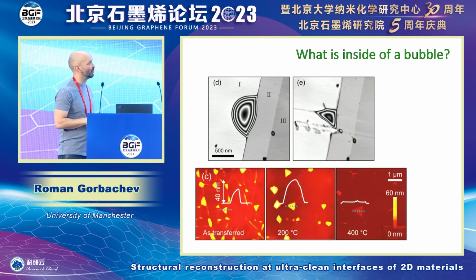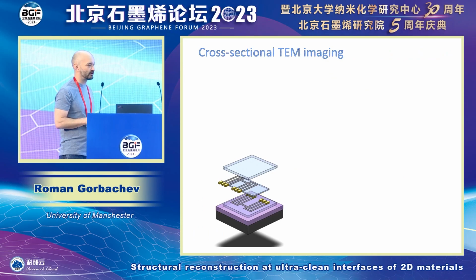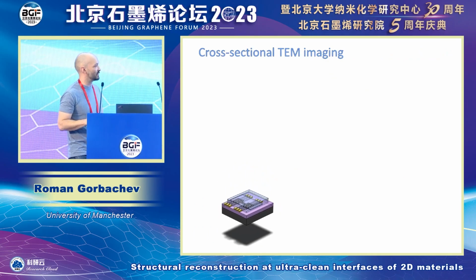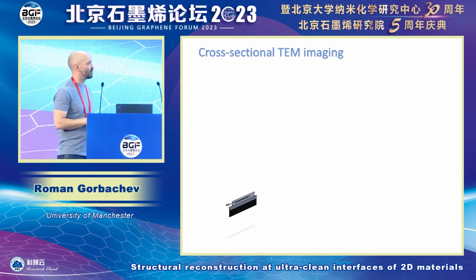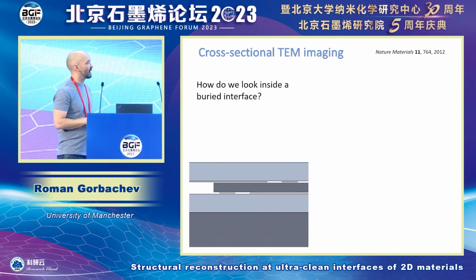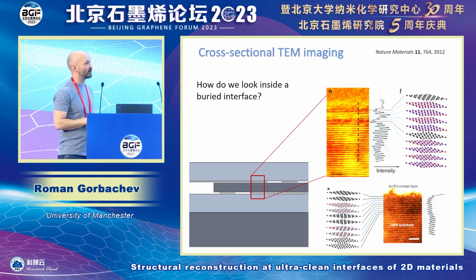back in 2010, we were looking at these pockets and we were looking at what they are made of. And really the key, what we've achieved is we took a focused ion beam, we cut a slice out of the sample, we put it in a transmission electron microscope, and what we see at the interface is individual layers, right? So this is, for example, graphene and boron nitride, and you can see that there is nothing in between them. They are pristine and atomically clean. So that was a huge surprise for somebody who does, for example, material science or vacuum technology, that in air you can make something atomically clean like this.